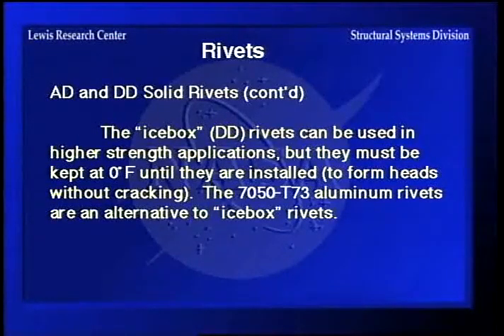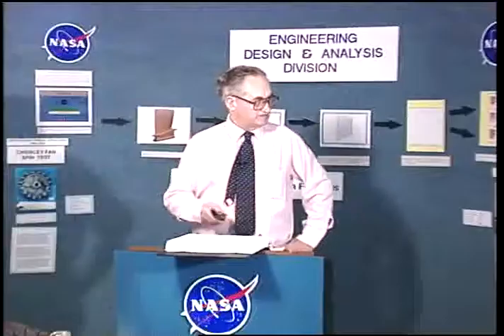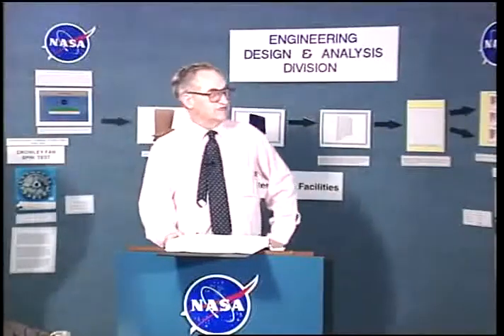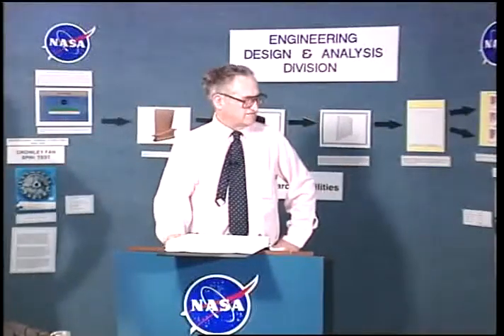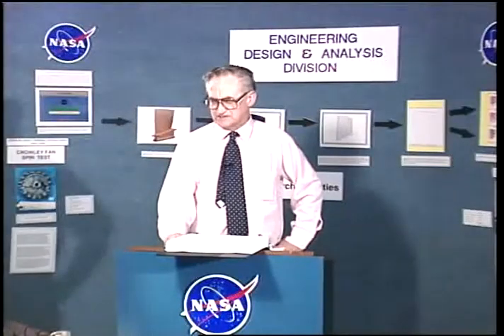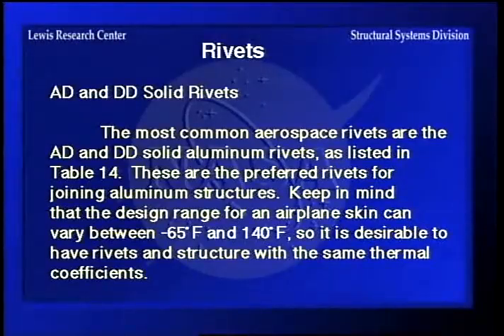Because when you think of it, at 45,000 feet you have about minus 65 degrees temperature, and on the runway out in Phoenix you have about 140 degrees on the skin. So you need to have rivets and skin that are very close metallurgically in order to prevent differential thermal loads. They had some trouble and had to change to fasteners that were exactly the same material as the skin in order to get away from that.